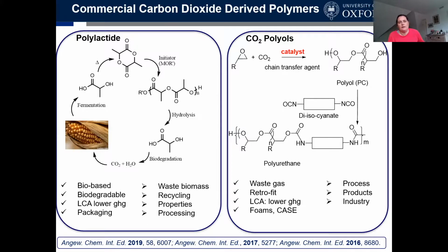On the left-hand side is a polymer that has the alternative way that CO2 might be used, and that's through intermediary trapping of the carbon dioxide through photosynthesis into sugars in plants. And then those are fermented to give you a lactide at the top of the slide, and that can be polymerized to give a plastic. And this polylactide is a leading bio-based plastic. It's one of the larger volumes, about 1 to 2 million tons of this plastic are made every year worldwide, and it's biodegradable. And it certainly has lower greenhouse gas emissions than incumbent plastics like polystyrene or polypropylene, and has some applications in packaging, but there are still some things that need solving about polylactide chemistry.